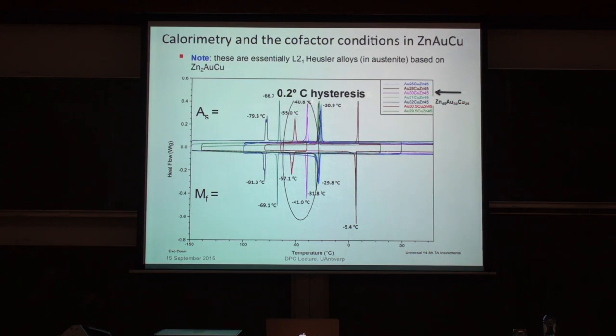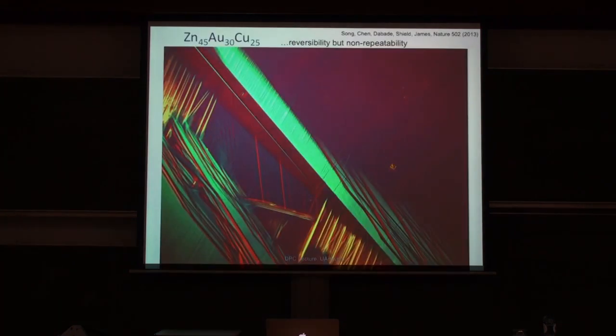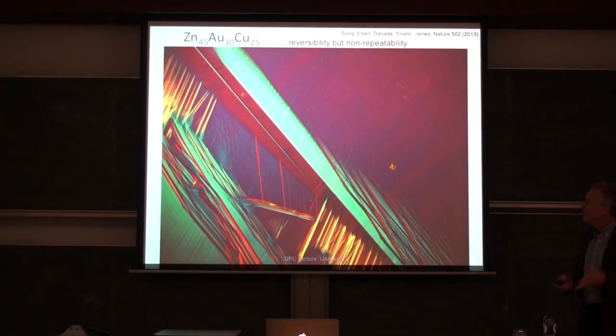And this is a measurement in calorimetry of the size of the hysteresis. There's a particular way of doing this that I won't describe, but anyway, this particular measurement has 0.2 C hysteresis. So that's really amazing for a first order phase transformation. 6% strain, this is a big first order phase transformation. And I'll show you a little, it's quite nice to look at, because usually in phase transformations, when you change the temperature, cycle it back and forth through the phase transformation, you get the same picture going forward and backward, and same picture from cycle to cycle. That's very typical in phase transformations. Usually thought to be mediated by defects and so forth.